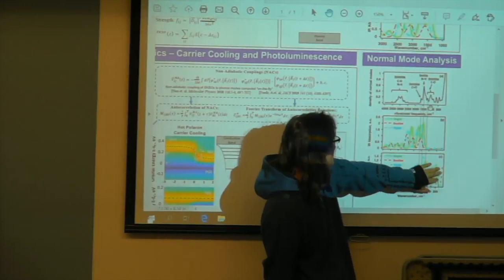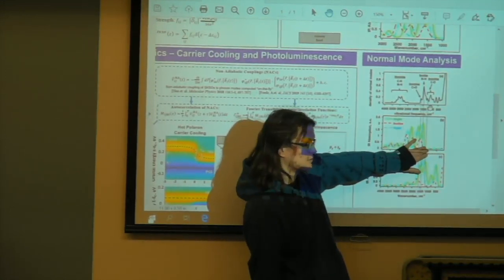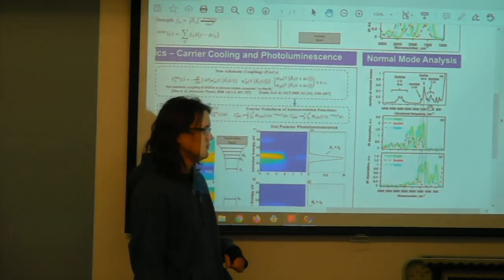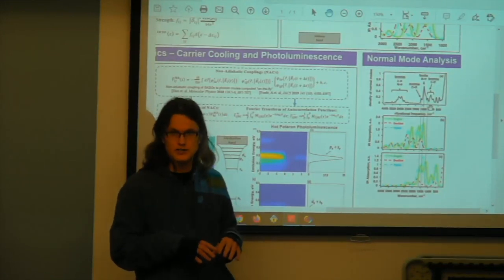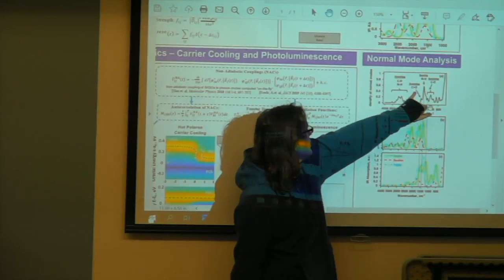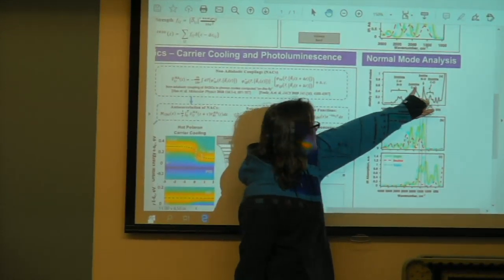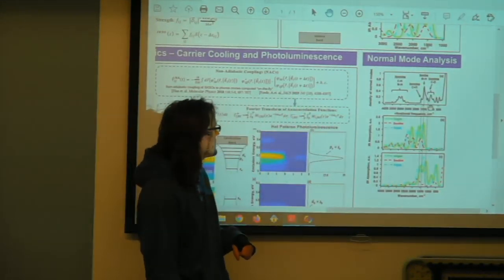Then when you consider the negative polaron, its transition energies are higher than what's provided by the perovskite lattice itself, but it also gains contributions from the surface vibrations from the ligands, which are the CO stretching from carboxylates and from the amine.